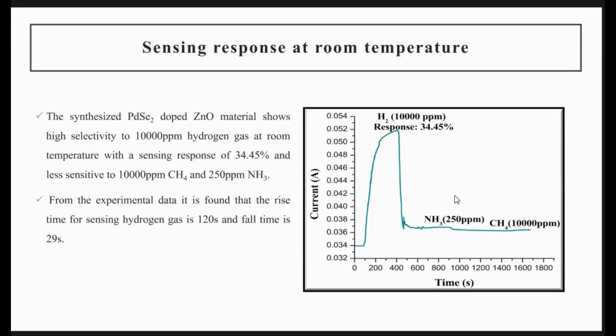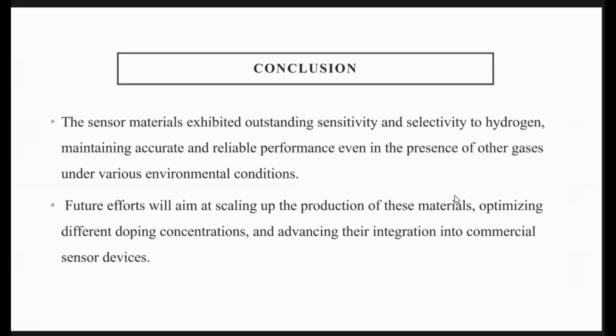And see, the other gases are not at all showing any response compared with hydrogen. We used 10,000 ppm hydrogen gas and 10,000 ppm methane, but methane is not at all showing any conductance. And the rise time is 120 seconds and the fall time is 29 seconds. So our sensor material showed excellent selectivity towards hydrogen compared to other reducing gases.